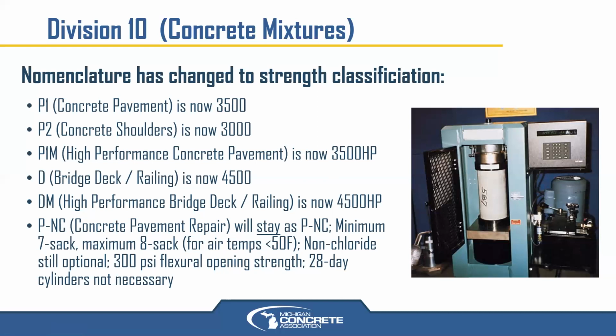That's where you're breaking a beam versus a cylinder like we see pictured here. You are not doing cylinders for pavement repair projects. With that PNC mix, you never cast cylinders or break cylinders like you see here in the lab at 28 days. Once the beams have achieved opening strength, then the patch is paid for, and there's no reason to wait more days in order to get a strength number. We're relying entirely on flexural strength for concrete pavement repairs and full depth patches. That for P-NC is a 300 PSI.